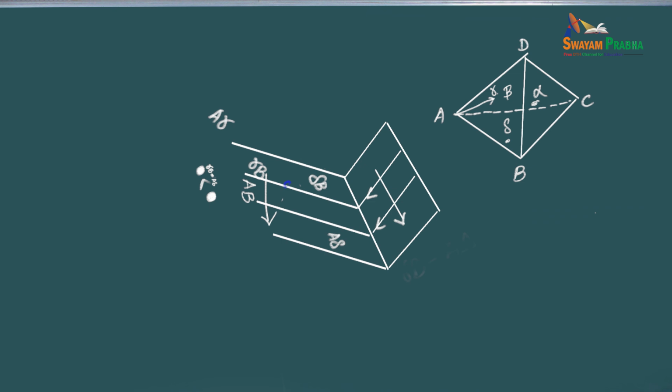I did that a long time ago, but I always found this fun because now there's one more step, which is that you know that the Burgers vector has to be continuous, constant along the line. So here, if I have a Burgers vector A delta here, and I have a Burgers vector gamma B here, it is not possible unless there's another dislocation here that connects this node with that node. For example, in this direction.